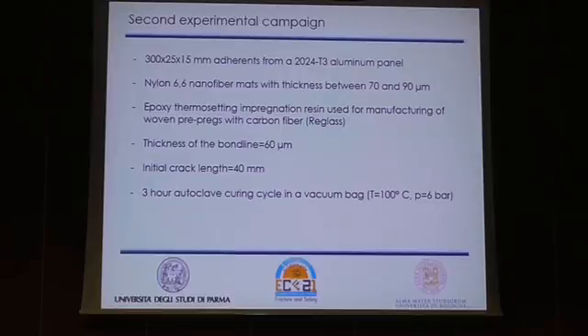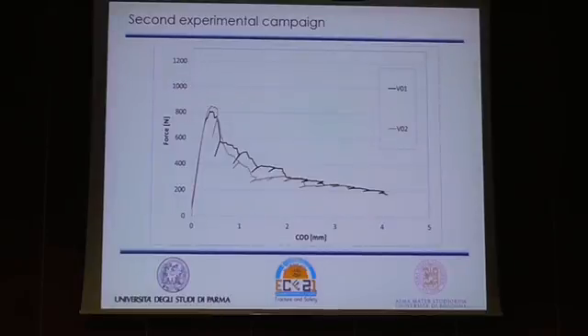Some 60 micrometers thick metal sheets were placed at both extremities of the specimen in order to make the thickness of the virgin specimen as uniform as possible with respect to the nanomodified specimen, in which, however, the metal sheets were placed to assure that the nanomat occupied the whole thickness of the interface, even if it had been squeezed during the curing process. And the vacuum bag went into a 3-hour autoclave curing cycle at a temperature of 100 Celsius degrees and a pressure of 6 bar. These are the results.